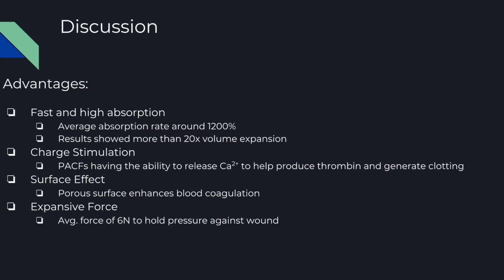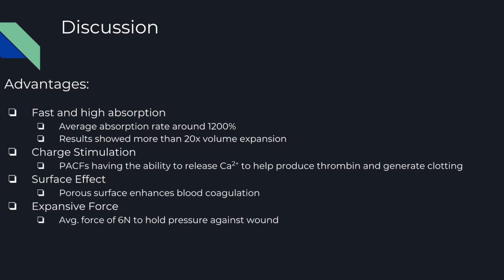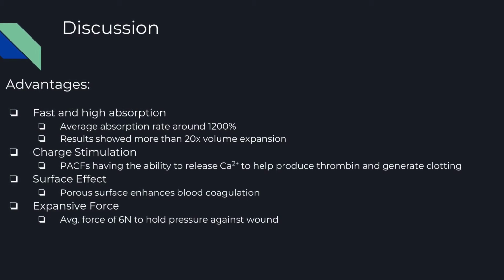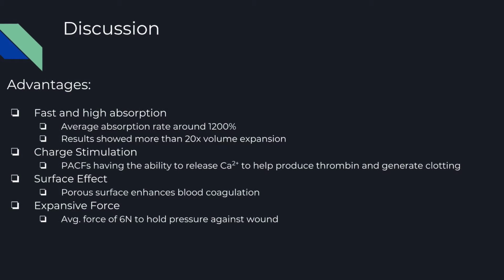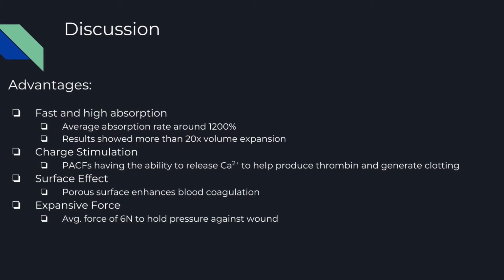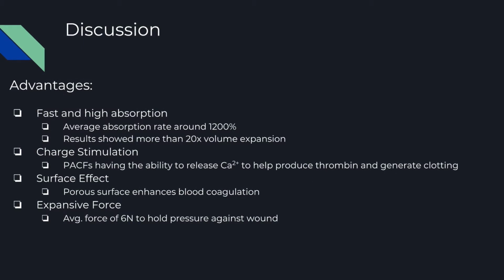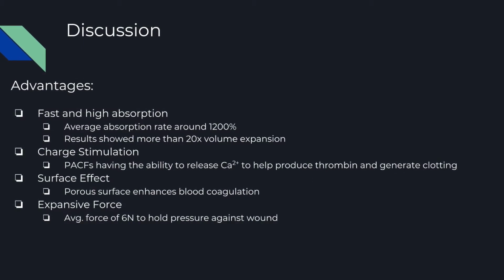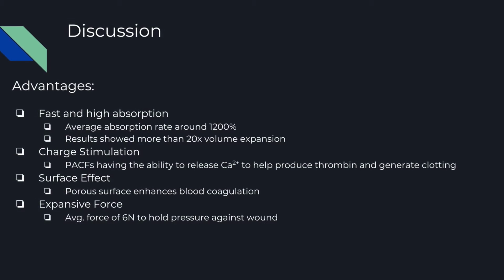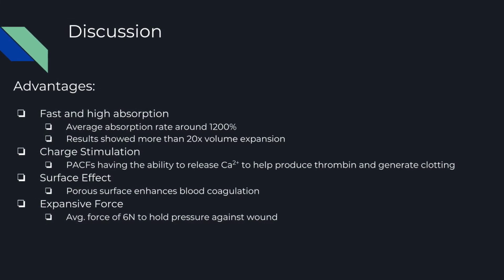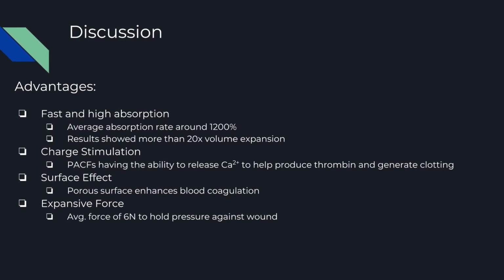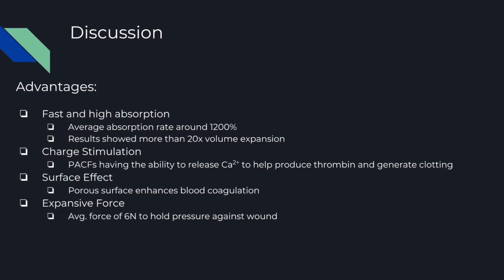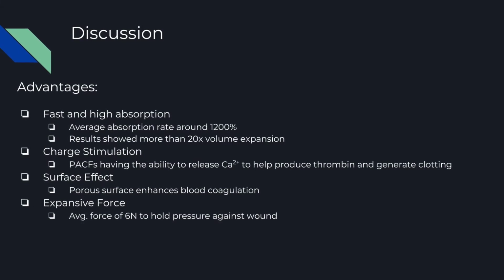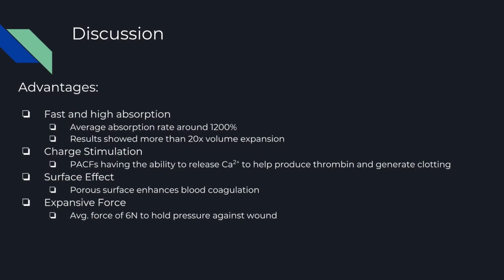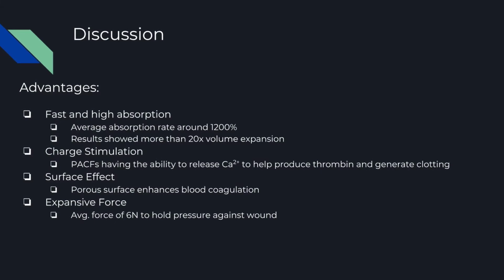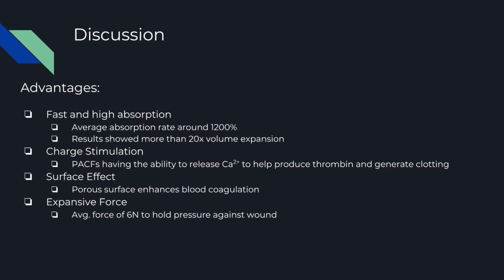The second advantage of the PACFs is the charge stimulation. The charge stimulation is related to factor 12, a serine protease zymogen in the plasma that interacts with the negatively charged networks of the PACF. The activation of factor 12 diffuses into the plasma and triggers the intrinsic pathway of blood coagulation. The PACFs also have the ability of releasing calcium 2+ ions from the network into the blood. The calcium ions not only contribute to the activation of the intrinsic pathway, but also help to produce the thrombin to generate fibrin clot.